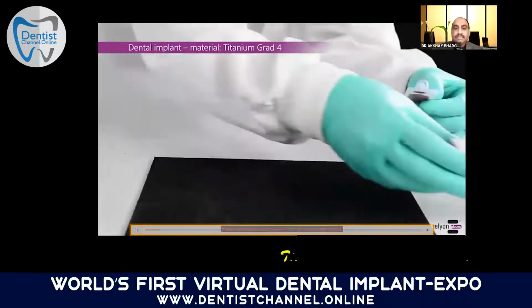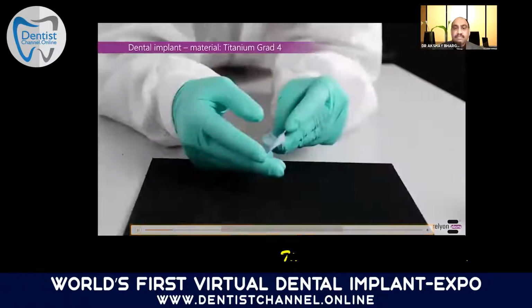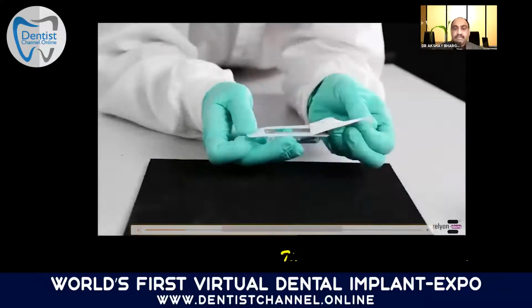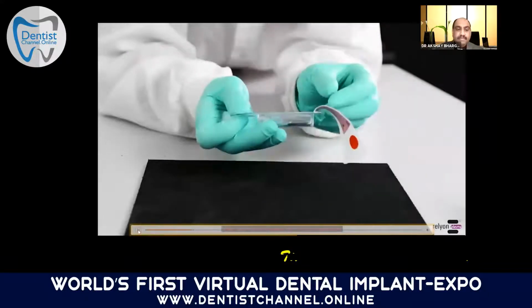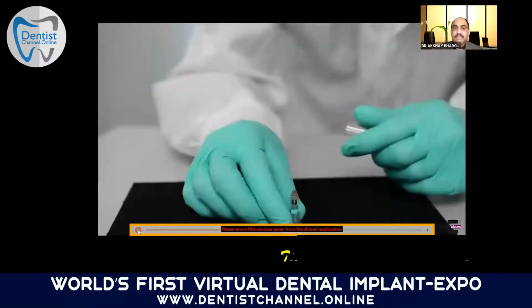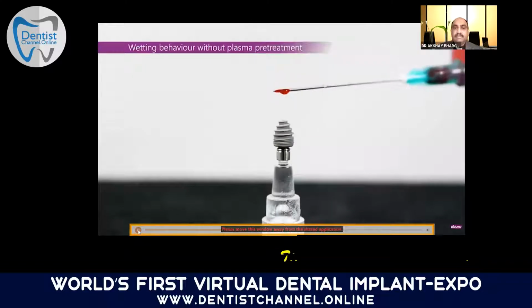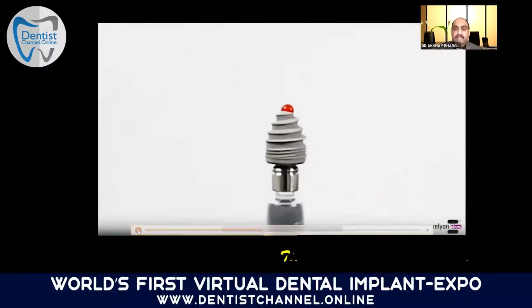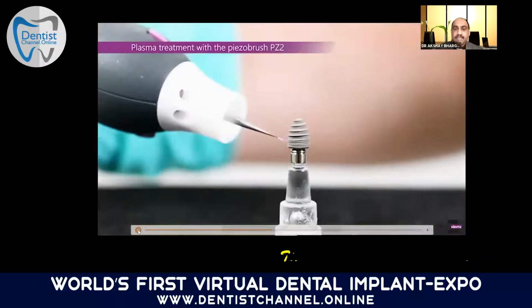It is important for the healing process after implantation that implants are wettable. We have investigated the wetting behavior of two titanium implants before and after plasma treatment. Please see the wettability, and it is going to demonstrate how hydrophilicity is increased by plasma treatment. When applying the drop, we see that the untreated implant is hydrophobic. The implant wets poorly. The second implant is now treated with plasma.